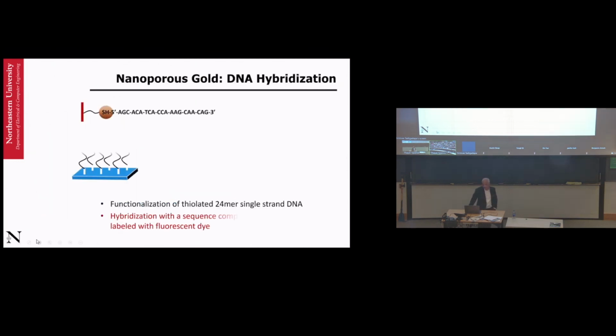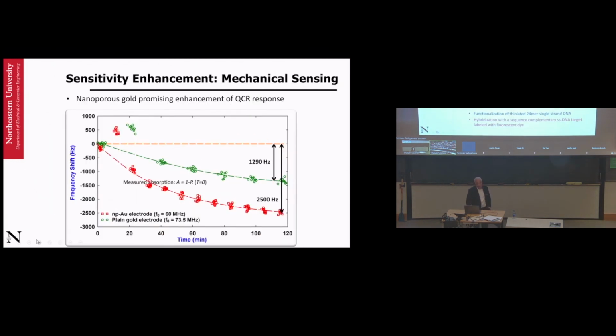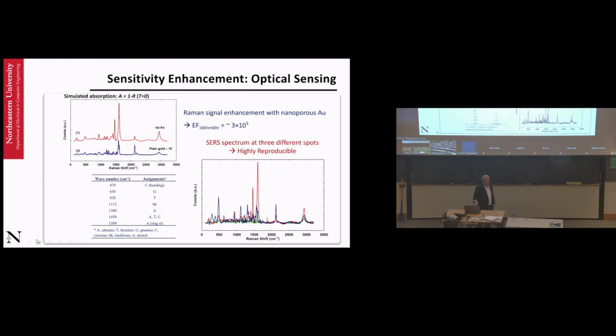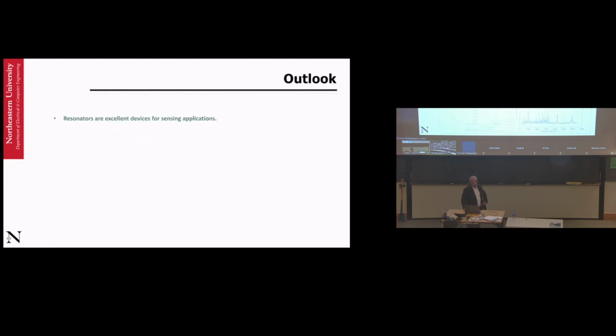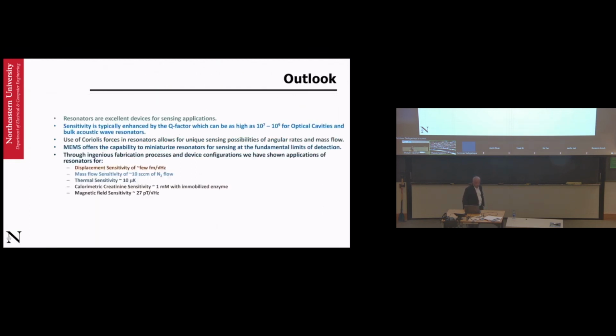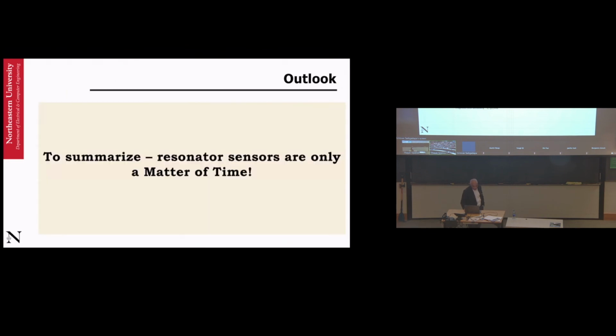And what we were trying to do was use DNA binding tests. And we actually integrated this on the quartz. The mass gives you how much DNA, and the Raman spectroscopy essentially tells you what you're looking at. And so the signal is heavily enhanced because of this resonance. Overall, I wanted to keep to the theme of resonance and show you that there are very different forms of resonance: optical, acoustic, mechanical. No matter which one you use, if you ask me, resonance is the way to measure everything. And that's my summary for you.